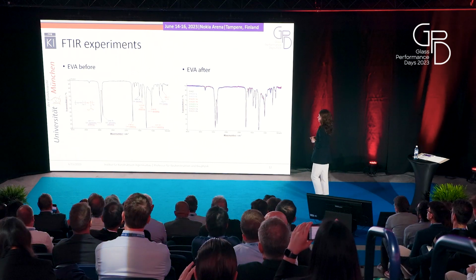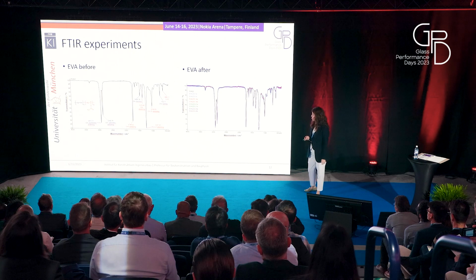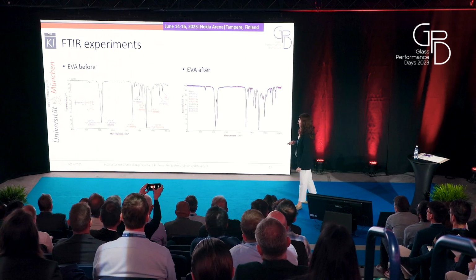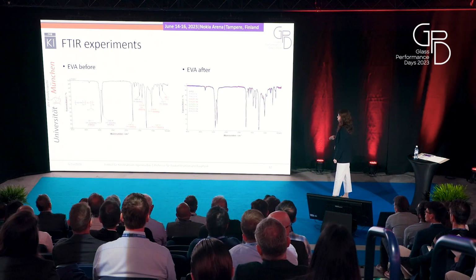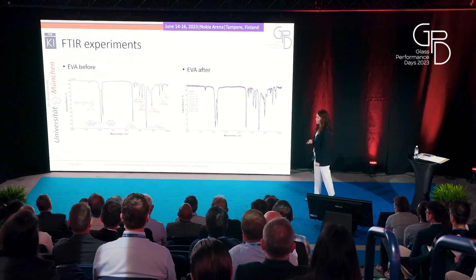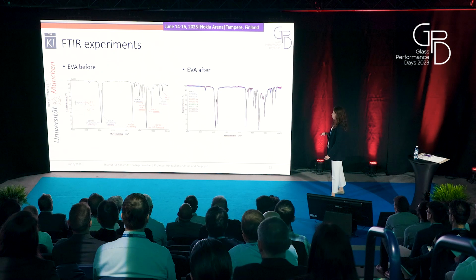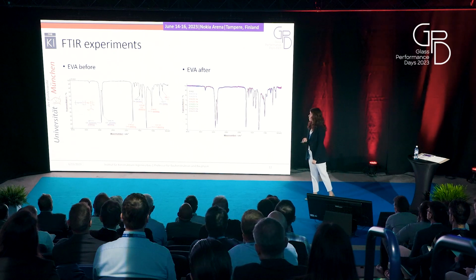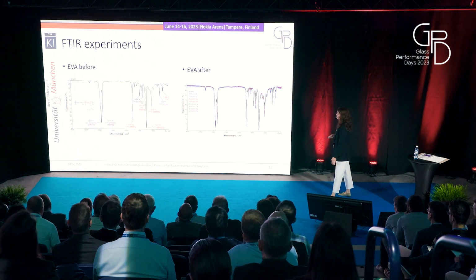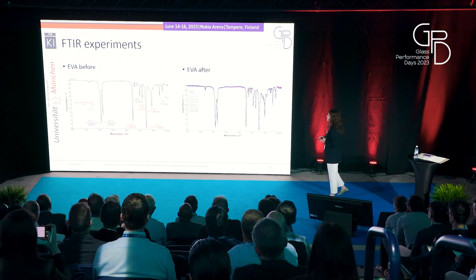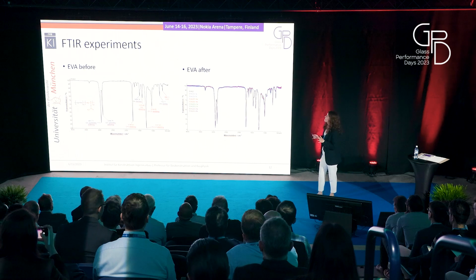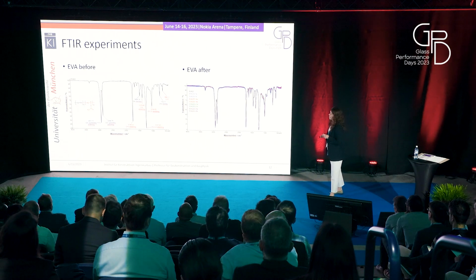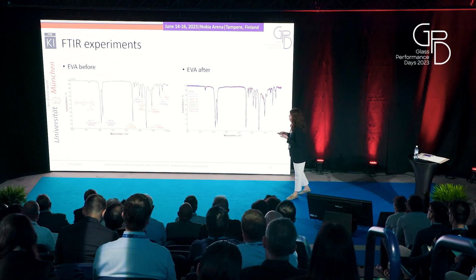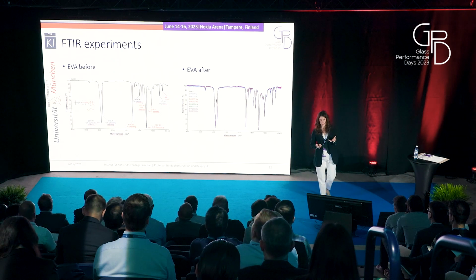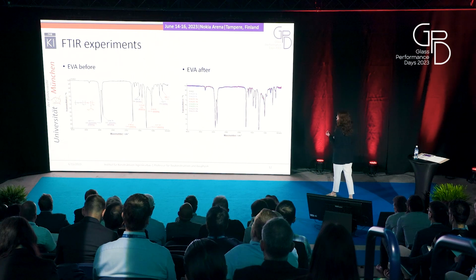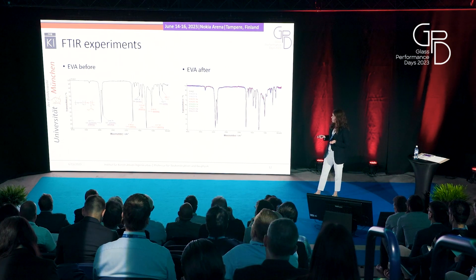And now, when we go further with our results, these are results of the infrared spectroscopy. So again, on the left are actually results of the EVA before it was exposed to humidity experimental program, and then on the right, the EVA after. What we can see on the right are the curves all put together: the EVA before it was exposed to humidity, then for 7 days, 14 days, 21 days, 28 days. So the overlapping is not 100%. It's not that they completely go one over another, but also the difference is not so big. So what does this diagram actually mean? That means that there is some water uptake with the EVA samples, but again, nothing so crucial, nothing so big.